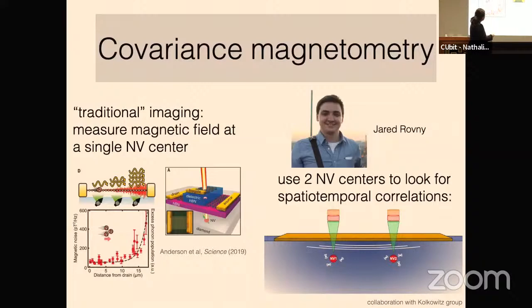In this case, this is work from Misha Lukin's group where they put graphene on top of a diamond, and then they're looking at transport signatures in the graphene. And what they're essentially doing is looking at individual NV centers and doing noise sensing, in this case, that arises from electron-phonon coupling during transport. Okay, and most NV sensing is some variation on this theme, where you're either looking at the magnetic field projection at a single point, or you're using the NV center to learn something about the noise environment.